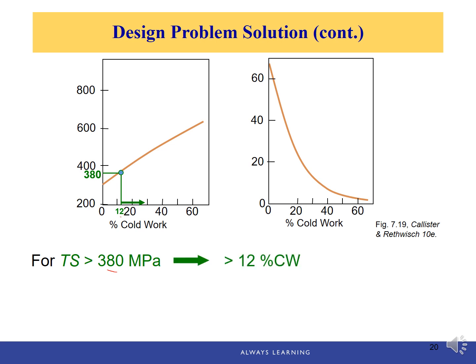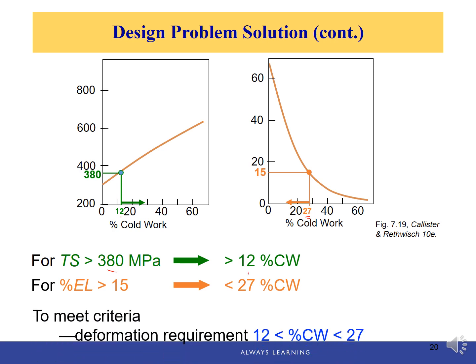And now for the ductility, it needs to be at least 15%. For 15% of ductility, we need to have 27% of cold work. And again, to have more ductility, we need to decrease the amount of cold work because ductility decreases with cold work. Therefore, we have to make sure the amount of cold work is less than 27%. Okay, now we have the range for the second stage cold work, which must be between 12% and 27% to have the desired strength and ductility requirements.